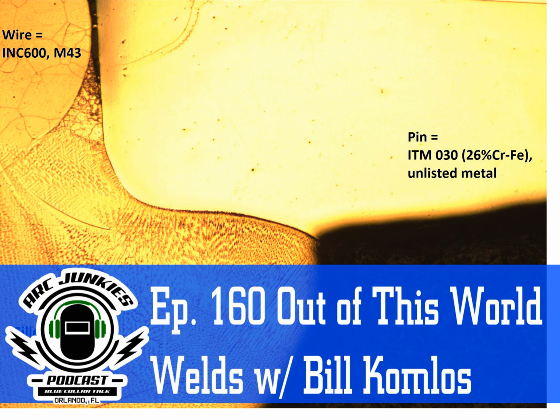Well, the austenite will act as a shock absorber in the joint design as well, but you need some ferrite so it doesn't hot crack on you. Well, you can see you've got no austenite in this. The austenite, the nickel, is what's showing up in these brown colors in the pictures. So this wire being an Inconel, it's got a lot of nickel in it, and that's why we see the wavy lines through it. This filler metal is at least 68% nickel. That's why we have all those brown specks in there.